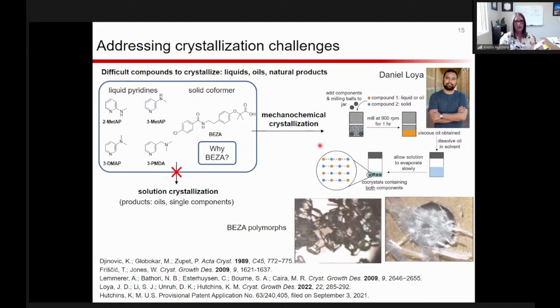And so you might think, well, that's exactly what you're getting from solution. But I was curious and pushing it a little bit further, so I told Daniel, let's take that oil and just dissolve it in an organic solvent and see if we can get crystals. And indeed, we were able to get crystals via this pathway. But if we skip the milling and just dissolve the two components in a liquid, we did not get co-crystals, or at least I'm going to show you one instance where we did, but it was not reproducible and not across the board. But this milling step allowed us to get co-crystals via this pathway.